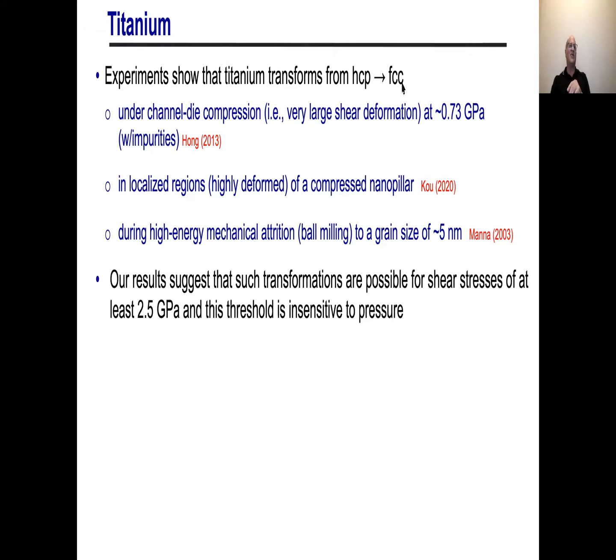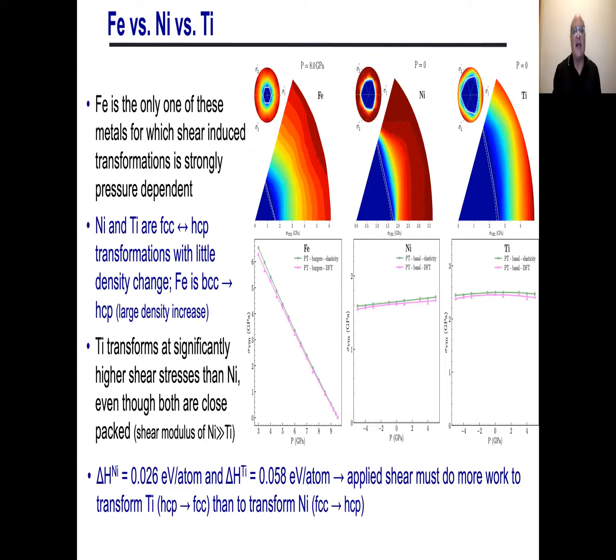Okay, unfortunately, our value is about 2.5 GPa, and it's pressure insensitive, but there's no data here to really make a quantitative comparison with. But the trends are the same. As you go to higher and higher shear stresses in titanium, you get more of this HCP to FCC transition. Okay, this is my last slide before I put out the conclusions. I think I've been talking a little bit too long already, but there is only one slide beyond this one.